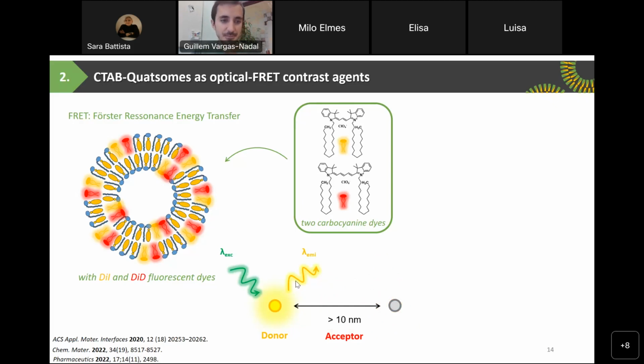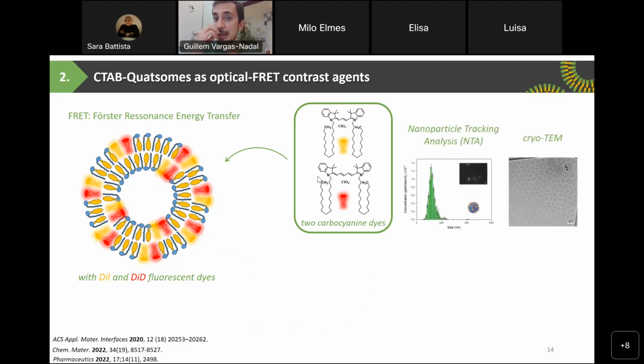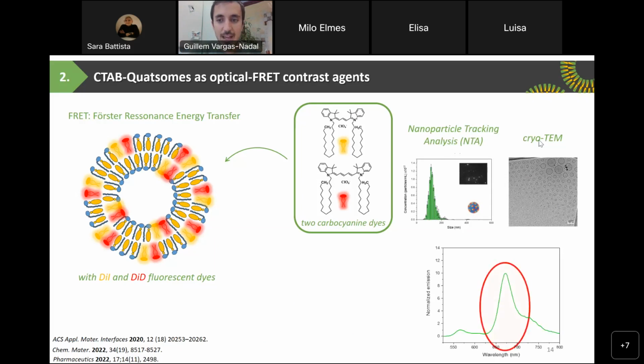With that, we have prepared these CTAB quatsomes with these two dyes, and we also characterized them. Here you can see in the nanoparticle tracking analysis result that they are homogeneous, and in the cryo-TEM image you can see the morphology of these quatsomes. In this case, you can see that they are spherical and homogeneous, and also they have only one lamella.